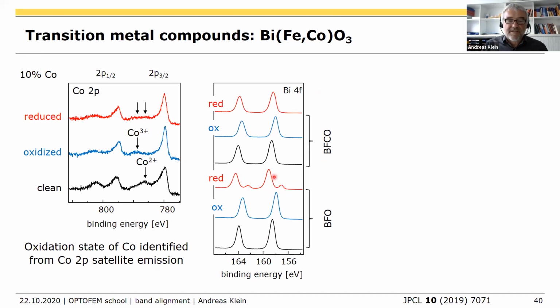The cobalt doped sample is similar. The oxidation shifts to lower binding energies, and after reduction shifts to higher binding energies. So these three spectra correspond to these measurements. But in this case, there is no metallic bismuth. And if you look at the binding energies, even here after reduction, the Fermi level is not as high as in principle for the clean surface when we have the cobalt 2+.